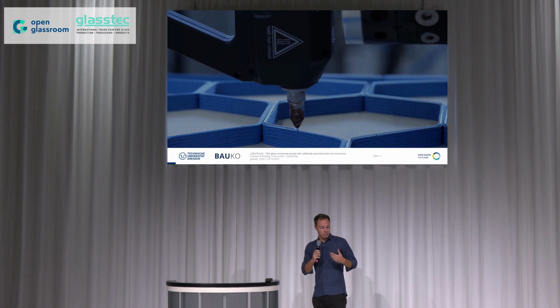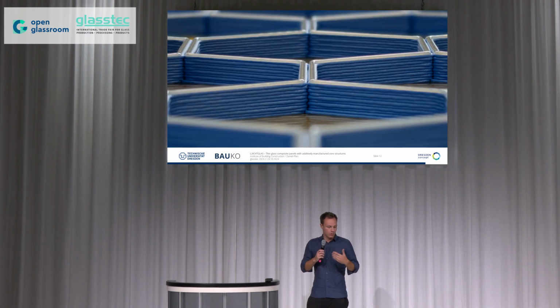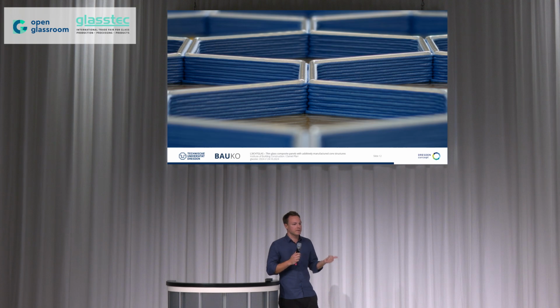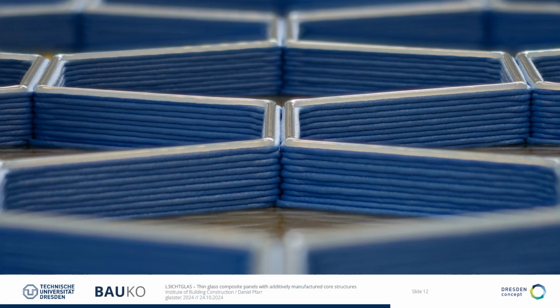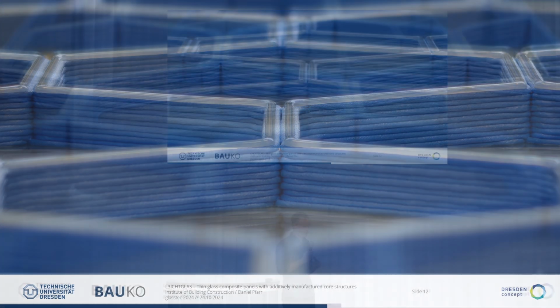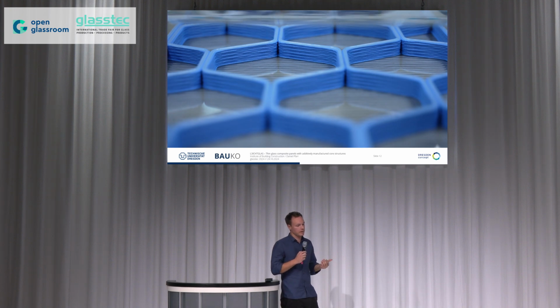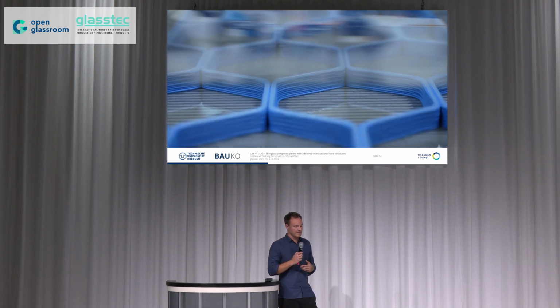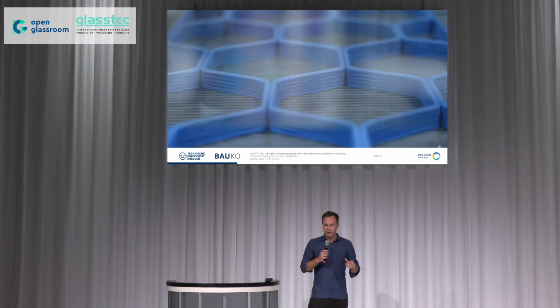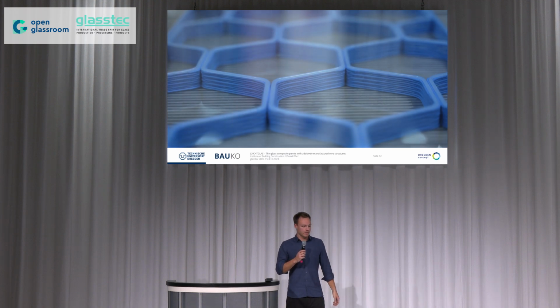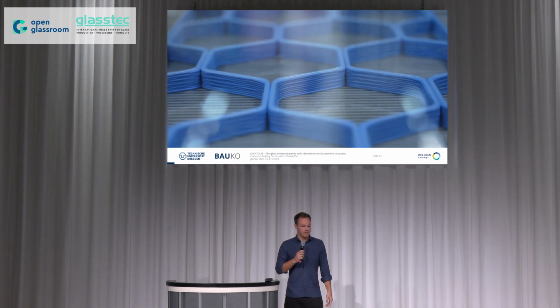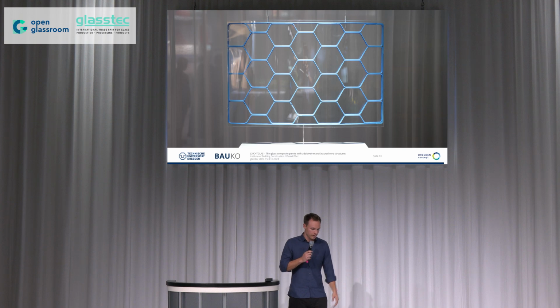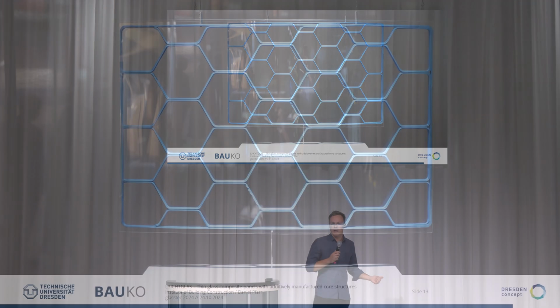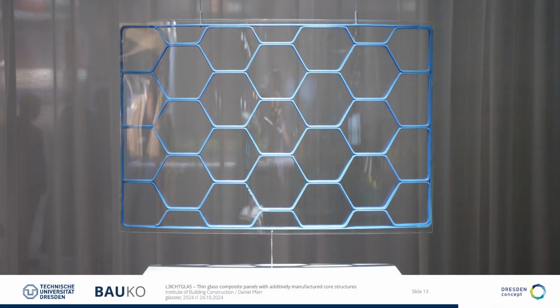And then the hot melt cools down and solidifies, like you can see here in this picture, when everything goes right and it looks very nice printed and the adhesive is nicely applied. Then finally we can stack the glass on it, and that is a thin sheet glass layer. And if everything goes right in the end and comes out of the lamination process, then we have a thin glass composite element, which you can see here in the picture, as well as a demonstrator just 20 meters behind me.